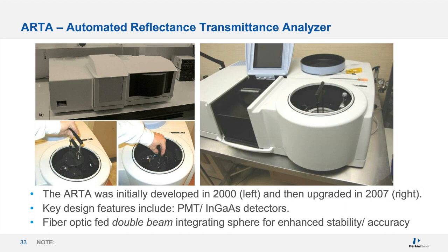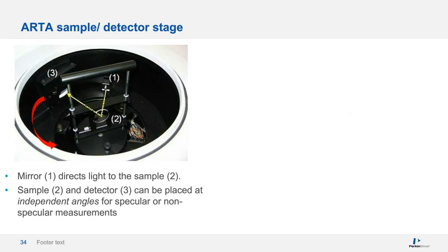Here on the left, we see the ARTA sample compartment. The 60mm detector sphere labeled number 3 can be seen to rotate around the sample, placed at the center of the accessory compartment. Mirror 1 directs the sample beam towards the sample, in this case a piece of glass, such that the detector is collecting specular reflectance data. Note that the detector could be moved to any angle to collect off-angle data or even scatter data for BRDF or BTDF type measurements if needed.